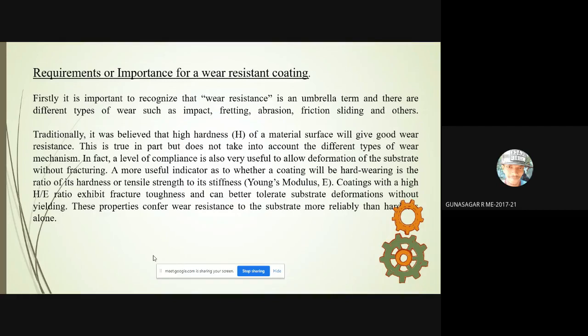Traditionally, it was believed that high hardness of a material surface will give good wear resistance. In fact, a level of compliance is also very useful to allow deformation of the substrate without fracturing. A more useful indicator for a coating will be hard wearing. Hard wearing is the ratio of hardness to its Young's modulus. Coating with a high hardness to Young's modulus ratio exhibits fracture toughness and can better tolerate substrate deformations without fracturing. See you in the next slide.